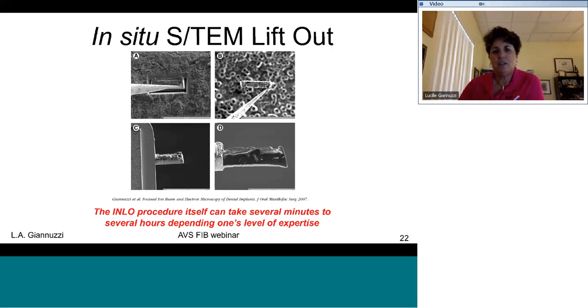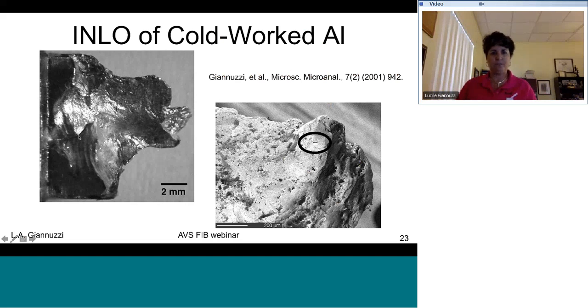Okay. Then you move your sample to the grid, and then you use your platinum deposition again, or whatever FIB deposition you're going to use, to attach the sample to the grid. And then you FIB mill the probe away, and you're left with this freestanding chunk of material that you can subsequently FIB mill the way you would do any other H-bar type of technique. So this procedure itself can take several minutes to several hours, depending upon your level of expertise.